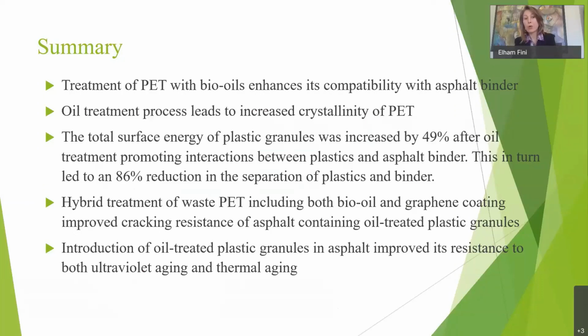We also show that this whole improvement is attributed to the biografting, which increases the surface energy dispersion forces after oil treatment. So an 86% reduction in segregation was observed in this scenario, and that was attributed to enhancement of surface energy, surface interactions. And reduction of segregation is exactly what we need to be able to use plastic within the construction material without it rejecting it. By rejecting it, I mean separating. So this is very important, and 86% reduction was pretty impressive.